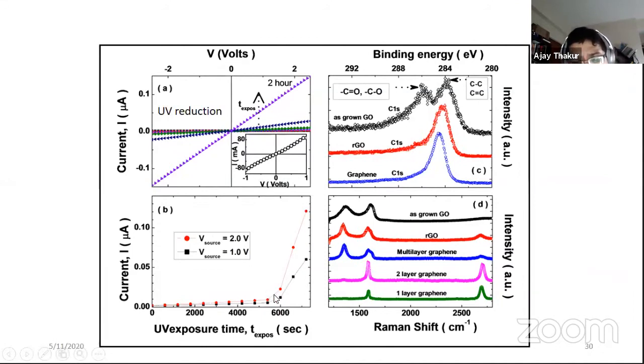And suddenly, at about 6,000 seconds of exposure, beyond that, there is an avalanche. After that, as we go to 3 hours, 4 hours, 5 hours, the current generated is very, very high. Therefore, through UV reduction, we are able to achieve very high quality reduced graphene oxide samples. Here we have shown the avalanche region.